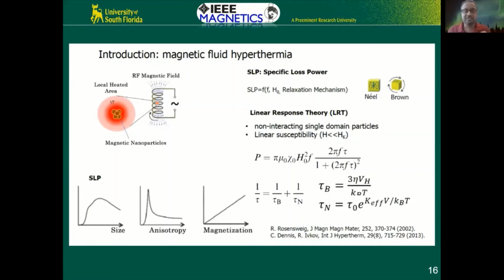For health reasons, you cannot use very small particles for hyperthermia treatment, okay? And this is because if you take nanoparticles less than 10 nanometers or 5 nanometers or less, the chances of these particles penetrating the so-called blood-brain barrier is very high. Which means these particles end up going to the brain, the wrong place where you want these magnetic particles to go. When you inject them into the human body, you want them to do their job, kill the cancer cells, and then basically go down south, flush out of your system, go down south to Florida, okay? So that's what you want. For health reasons, it's very risky to inject very small particles. So there is a limit. You cannot use particles that are really small for hyperthermia. So we have to be careful about that.